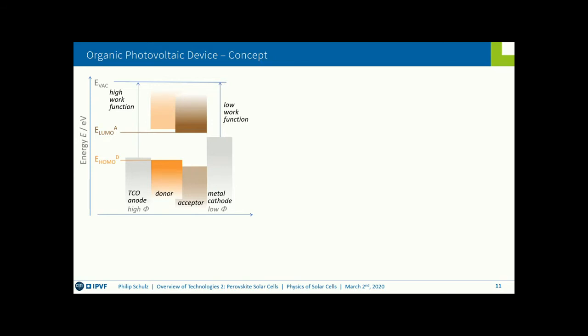Okay, moving on. I said already, the conduction band on the acceptor molecules corresponds to the LUMO level. The valence band would correspond to the HOMO level on your donor polymer. And in order to extract from here to here, you need a high work function TCO anode in general. So this is a very rough guideline. It's not that easy. We will come again to this tomorrow. And the low work function metal cathode here on this end in order to extract electrons.